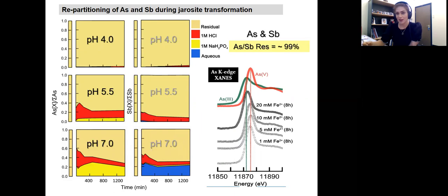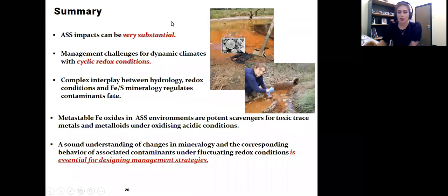So for our next experiments and the series of other experiments that we conducted so far, we applied all these parameters in our experiments, and we try to monitor the changes in mineralogy and in iron, sulfur, depending on which mineral we are looking at, and recently manganese, to see how the mineralogical transformation of iron and manganese minerals will affect the arsenic and antimony behavior in the presence of different concentrations of humic acid, or in the presence of bacteria, like a biotic experiment. But obviously I cannot cover all that research in this presentation, so I will wrap up my presentation at this stage and give you a summary of my talk.